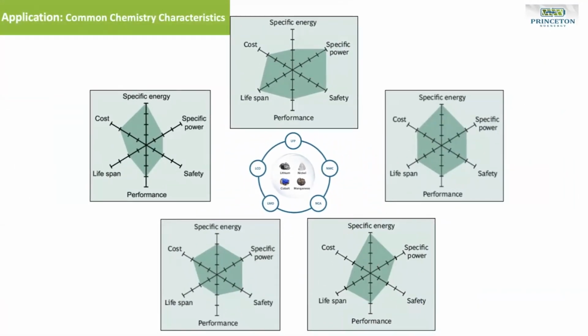Before that, I'm going to show they have different advantages from different materials. So for the LFP, the material on the top, this is a very safe material and has a longer lifetime. However, the energy density is a problem. So that's why in the US, the majority of EVs are not using LFP, because of the energy density. The US customer really wants the long range EV. So that's why in the US, we use NCM most. But in China, or some other regions, particularly in China, most EVs are made with LFP because the cost is really low and also it's really safe.